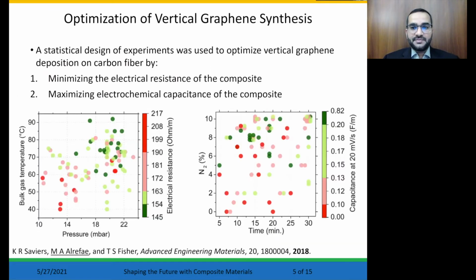In our design of experiment, we wanted to optimize 2 objectives. First, minimize the electrical resistance, and second, increase the capacitance of the composites because we intended to use the composite for supercapacitor applications. The electrical resistance was measured using a 4-wire Kelvin method, whereas the capacitance was measured using 3-electrode electrochemical cyclic voltammetry. We selected these 2 objectives because they can quantify the density and morphology of vertical graphene at reduced characterization cost.